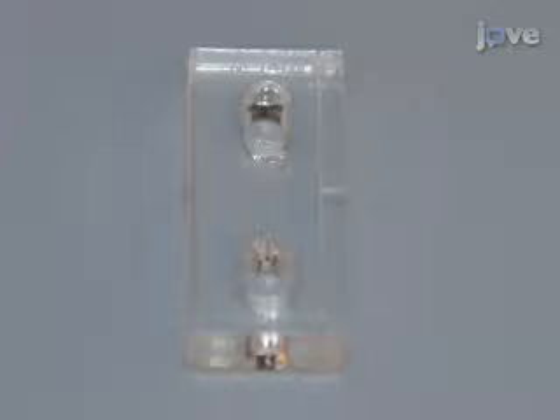microtensile tester. In this experiment, each holder is 11 mm by 7 mm with a thickness of 2.2 mm and has 2 holes to align with bolts in the microtensile tester. Laser-etched markings show the center line of the holder at 1.5 mm from the end. Each implant sample requires 1 acrylic holder.